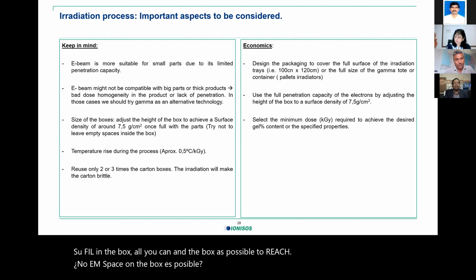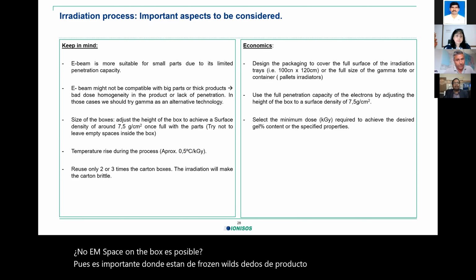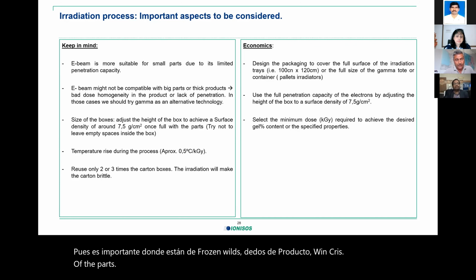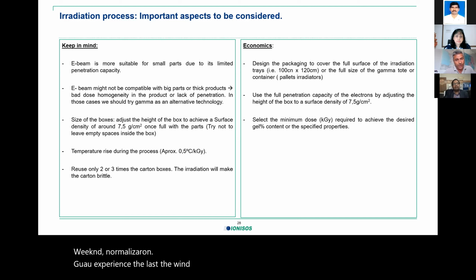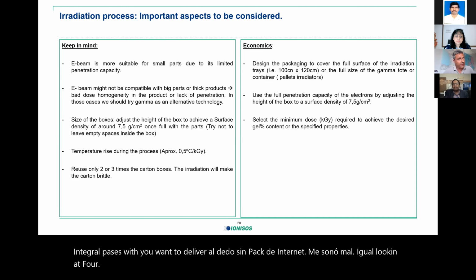Also, it's important to understand that the dose delivered to the product will increase the temperature of the parts a little bit. It will depend on the heat capacity, but our experience tells us that normally we will increase around 0.5 degrees for each kilogray that we deliver. So this means that we will deliver the dose, which is normally around 100 kilograys, in several passes. We don't want to deliver all the dose in one pass because the increment in the temperature will be too high. So normally we are looking at around 4-6 passes of treatment.